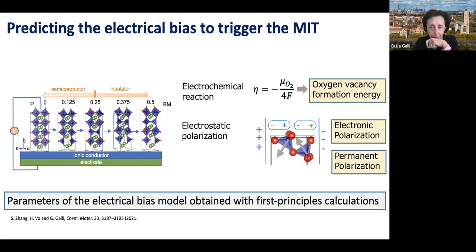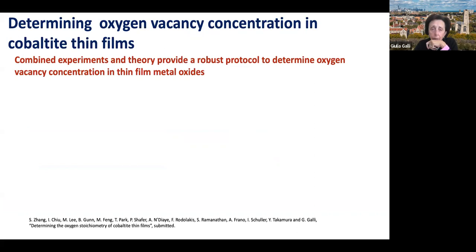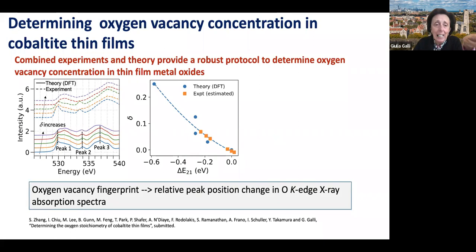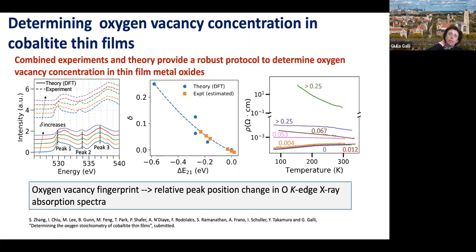And finally, by doing a really very integrated study with experiment and looking at an analysis of the X-ray absorption spectra, we identified the oxygen vacancy fingerprint in those spectra. And then we related those to experimental measurements of the resistivity and then to the electronic properties of the system. So I realize that this was incredibly fast, but I wanted to give you an idea that there are